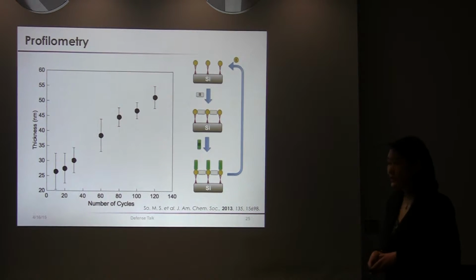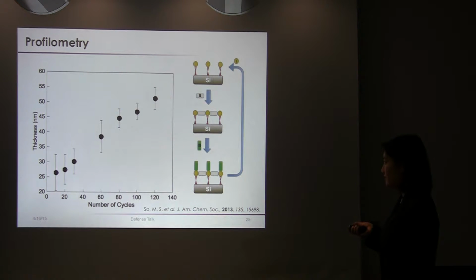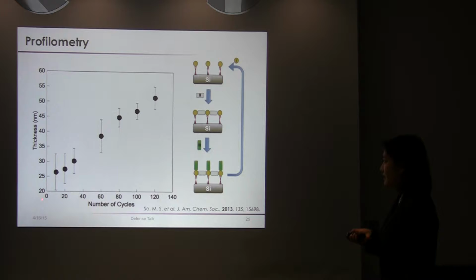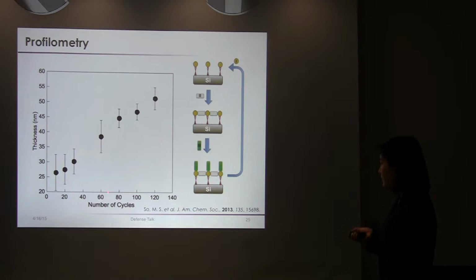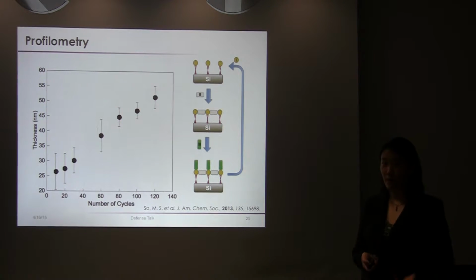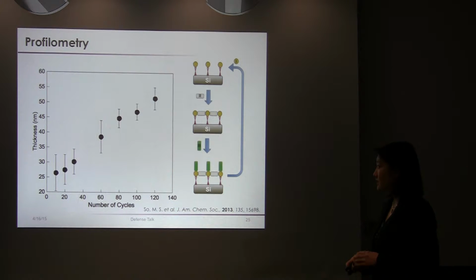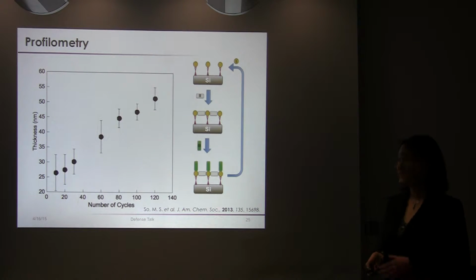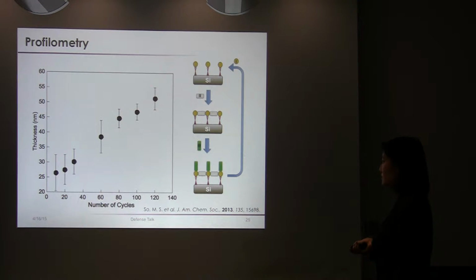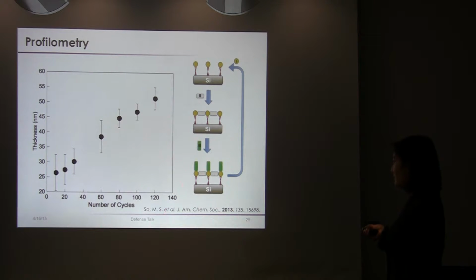So to monitor the growth, I did profilometry and monitored the thickness of the film growth as a function of cycles. And notice that from about 10 cycles to 120 cycles, the film growth goes from about 26 nanometers to about 52 nanometers. And this corresponds to a film growth rate of about 0.24 nanometers per cycle. And this is actually very good because this corresponds to about 1 molecular layer of growth per cycle, which is exactly what we want. And secondly, notice that the roughness decreases from about 6 nanometers to 3 nanometers in this case. And that corresponds very well to about 2 to 1 structural repeat units that are oriented perpendicular to the silicon substrate in this case.